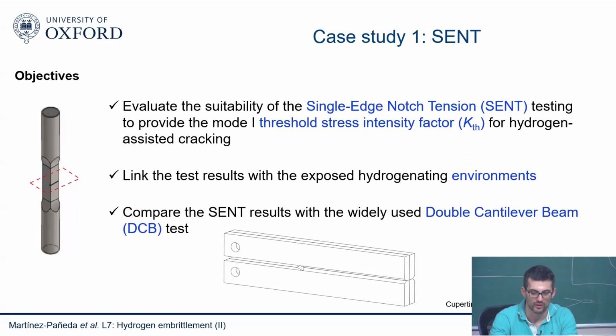And the idea is, the industry has these two tests. They don't know which one is more convenient to use. They don't really know what the duration of the test should be, but basically they want the simplest test possible to certify the behavior of these components in these aggressive environments. This one they prefer a bit more, the double cantilever beam, because there they put a wedge, and then they leave. It takes more time, but they just leave the sample in an aggressive environment with the wedge, and a technician can leave it there.